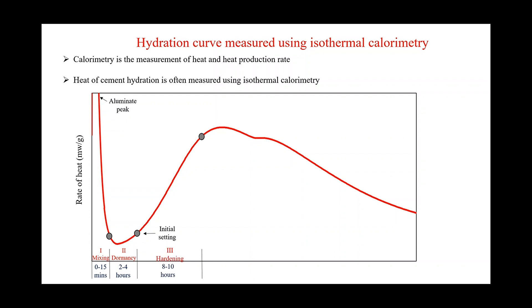The next stage runs from initial setting to final setting, lasting up to about 8 to 10 hours — this is the hardening stage and the most important stage of hydration. During this period, the solution becomes supersaturated with calcium ions, which were formed due to the dissolution of C3S.